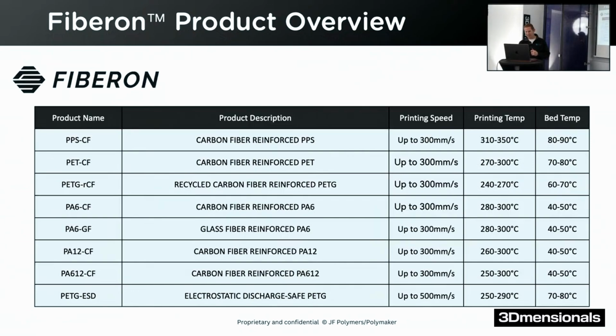So here we have also all these materials are optimized for high-speed printing, right? So we fine-tune the melt index and play with the molecular weight to make sure that we can keep up with the speeds that the current printers and our customers are demanding. And also another optimization is that you don't require a heated chamber for any of these materials. So they can all be printed on open or enclosed machines.